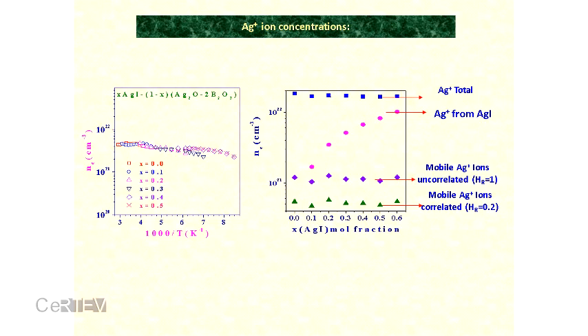We have taken two values. Haven ratio 1, that is, if the Haven ratio is 1, there is no correlation between charge carriers, there is uncorrelated motion. And if there is some correlation, I have taken the value of 0.2, there is strong correlation. But you can see that the charge carrier concentration does not change drastically, just by a fraction.